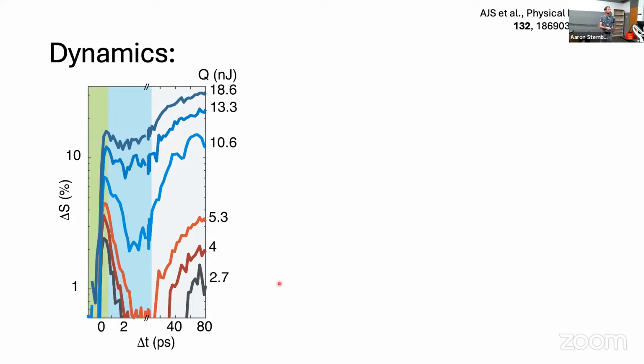Going on to dynamics, what we see is, again, an abrupt rise and then a decrease of the near field amplitude, so a recovery on the picosecond timescale, and then a follow-up increase of the signal. And all of this is fluence dependent.